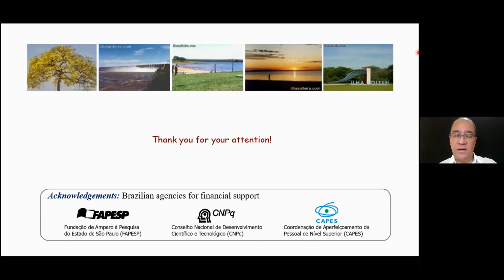Okay. Thank you. Yes, I understand you. As observed in my talk, sometimes you can introduce a specific atom in the structure, like lanthanum, zirconium, and niobium. But in my opinion, in this case, you are changing the nature of the BFO structure. You don't have the same structure anymore. The question is that not only oxygen vacancies are responsible for the physical properties, as often discussed in the literature. There are other possibilities like bismuth vacancies and iron vacancies. This result, in particular, suggests that complex defects must be investigated. I agree with you.